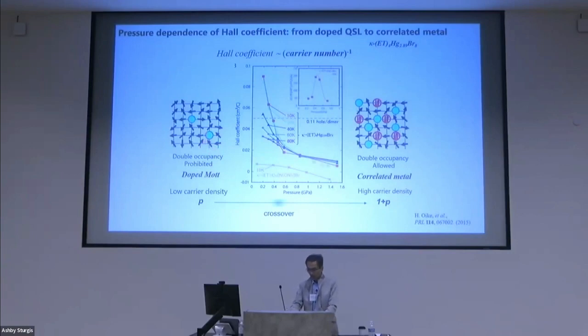Okay, and then it shows that all of the electrons participate in the conductivity, so we think that this is a small Fermi surface to large Fermi surface crossover. So this is a guess, and this corresponds to the crossover in this range of pressure, I think. Okay. So the interesting region is the low pressure range here for the doped system,